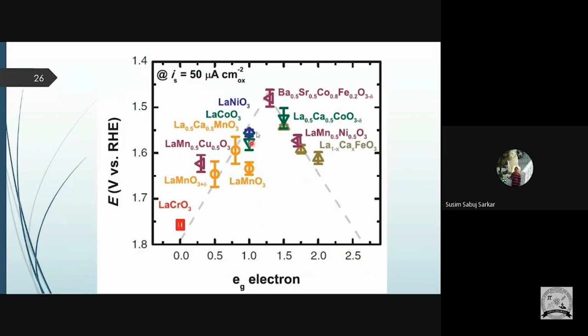Now here again are the perovskite oxides. You can see the same metals: lanthanum calcium MnO3, lanthanum cobalt oxide, lanthanum nickel oxide. These same materials also give very good activity for the OER reaction. That's why the reaction procedure is just reversed in the case of OER. Normally it performs with water, and when we give some electrical energy from an outer source, it does the opposite thing.